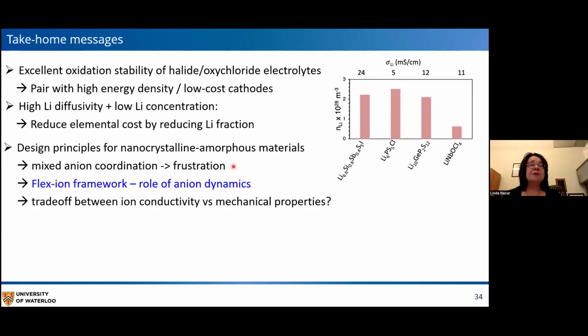And I hope I've described, or at least highlighted, some design principles for these nanocrystalline amorphous materials. I think we've really established what to do with crystalline materials, but these are much more difficult in terms of achieving design principles. What seems clear is that mixed anion coordination is important, which leads to frustration. We believe that many of these materials really benefit from the role of anion dynamics to create a flexion framework. And finally, of course, there's probably a trade-off between ion conductivity versus mechanical properties.